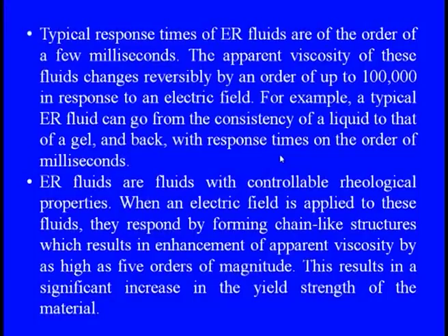So the typical response times of ER fluid are in the order of a few milliseconds. They are just showing this decay part, and the apparent viscosity of these fluids changes reversibly by an order of 1 lakh in response to the electric field. If you take one example, a typical ER fluid can go from the consistency of a liquid to that of a gel and back in the same manner, with response times on the order of a millisecond. This is a clear feature, which is why we say that ER fluid dampers or sensors are very sensitive.